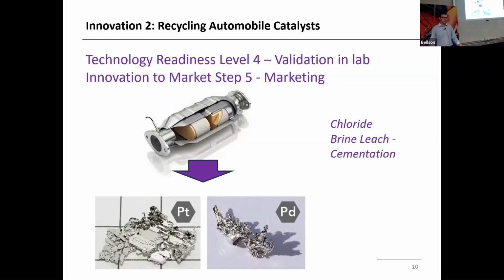They provided a bunch of these samples, and we did leaching trials, and we came up with a chloride leaching process where we were able to dissolve the platinum and palladium and then just cement it. We had a circular loop for the liquid going around, and we were able to get pretty good recoveries, and it was a fairly efficient process. So again, it was one we validated in the lab. We started marketing, but again, it's a pretty small local market. We engaged a little bit with some of the international people who are already doing different things, so they weren't super interested. So that one fizzled out for now, but it's still a nice idea, I think.